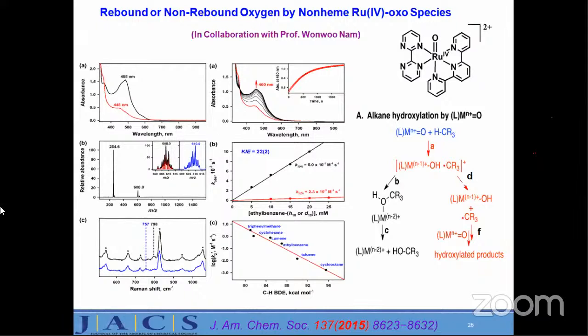Now when we added this, it happens like this. So we thought we would characterize it, and when we did, we found that it is actually a ruthenium 4 oxo species, which was very well characterized by ESI mass. You can see here the O18 labeling studies, H2 O18 labeling studies, all those things were done. And then we also did resonance Raman studies. So it was proved that the ruthenium is bonded to oxygen by this particular characterization method.